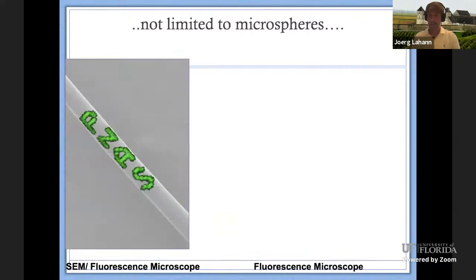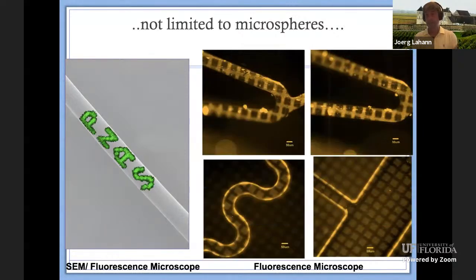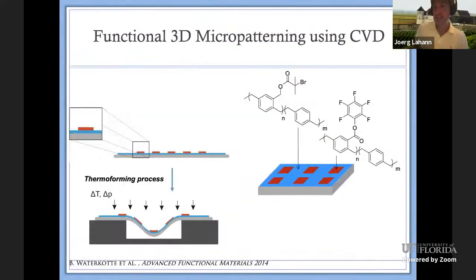Here's a human hair that was modified in this particular case, but it also works with microfluidic systems, with stents, for instance, which are three-dimensional, but also really with 100 micrometer glass beads, for instance. So the limitation in resolution here is really more coming from the projection lithography, which has become much better now than before. And so I think we could even go to micron or maybe even submicron, maybe not, but micron level patterns with those systems as well.